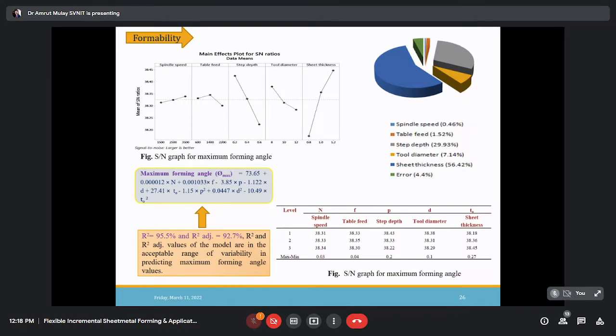Similarly, the study has been performed on the formability. In the formability study also, we conclude, here you can see the pie chart, that the sheet thickness value is very much important in case of formability. The more the sheet thickness available, the more material is available to form, right? More material is available to form, more power is required for the machine. So more will be the resistance from the material, right? And sheet fracture can be prolonged, right? So step depth and sheet thickness have a significant effect on the